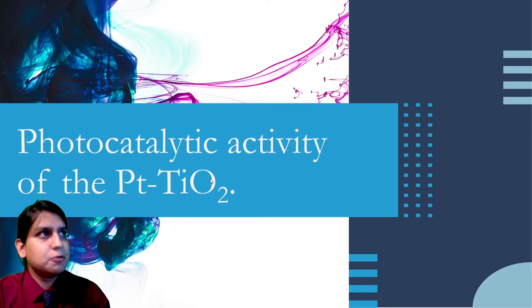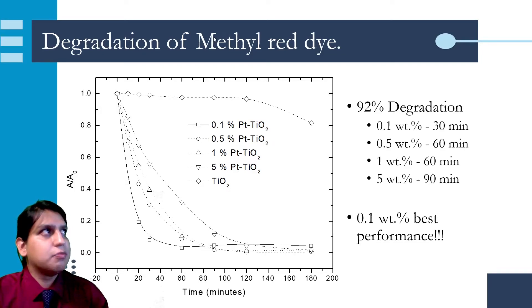Now I'm going to present the photocatalytic activity of the platinum-titanium dioxide materials. For the degradation of methyl red dye, we obtained 92% degradation of the dye in different times with different platinum loads, being the best performance obtained with the 0.1 weight percentage load of platinum material.